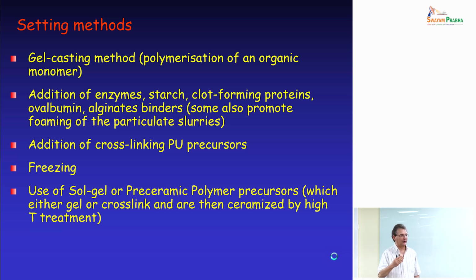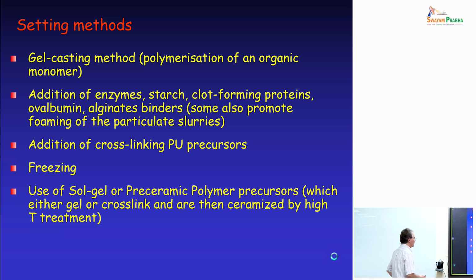Or you can mix your ceramic powder with a polyurethane precursor, and you can foam directly the polyurethane precursor, forming a solid. Or you can use freezing, or in my case, you can use sol-gel or pre-ceramic polymer precursors, and you have either gel or you can cross-link the pre-ceramic polymers.